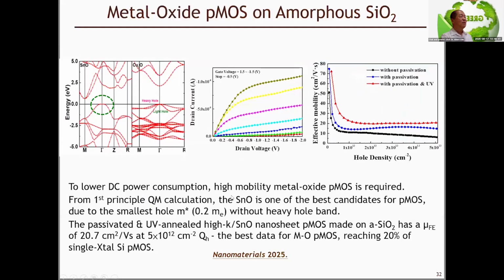How about the PFET? As we know, to lower the DC power consumption, high mobility metal oxide PFET is also required from the first principle quantum mechanical calculation. The tin monoxide is one of the best candidates for PFET due to the very small hole effective mass without the heavy hole band. In almost all the semiconductors, we have a light hole band and a heavy hole band. But in the tin monoxide, we have only one band.